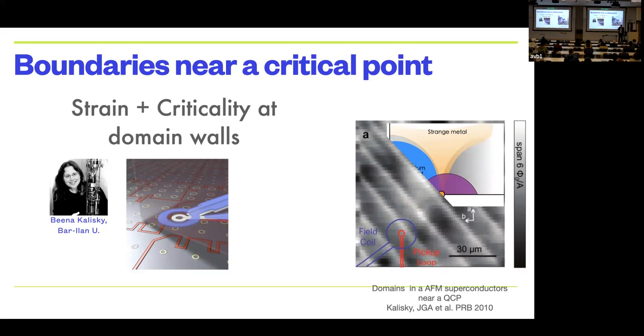So it got me thinking, is it possible that at the domain wall itself, you're basically tuning the critical point? Maybe the strain is that non-thermal parameter that is tuning you across this phase transition. So maybe I've got a magnet on one side and a magnet on the other, but in between I've created some way to tune across a phase transition. And that's perhaps why I'm tuning across that phase diagram across superconductivity. This idea has always haunted me. We measured this in 2010, and I always wondered whether you could actually have quantum criticality at these domain wall boundaries, even though the system on either side is not quantum critical at all. It was maybe nowhere near a phase transition. So I was always very interested in this idea.